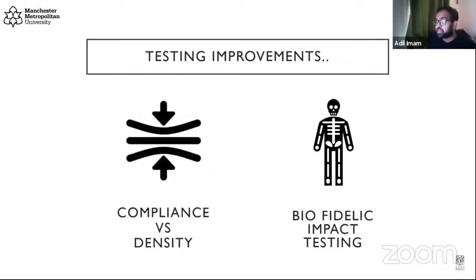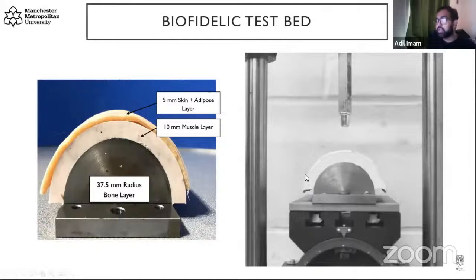One of the other things we did was develop a biofidelic impact test. Now the impact test that is there, steel on steel, not very realistic. This project is working in combination with a researcher at the University of Sheffield. Now Angus developed a test bed which is mimicking the shoulder area, a rigid core with a muscle layer and a skin layer on top. And we carried out some stud impact testing to mimic what would actually happen if a human skin comes in contact with the stud, which is usually worn in the game of rugby. So we carried out some impact testing, and I'm just showing the video of a perpendicular impact, but we did impacts at different angles as well.